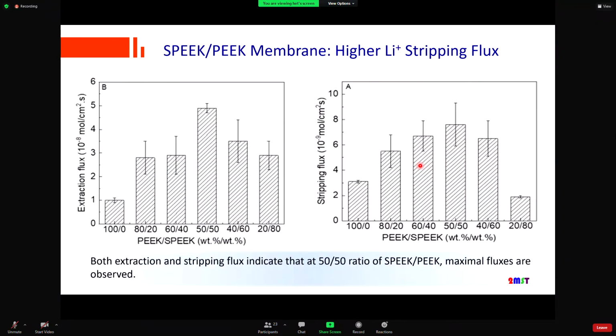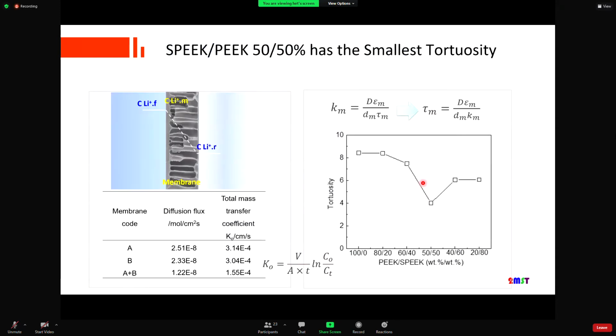For extraction and stripping flux, the two figures show that at a 50-50% ratio, we have the highest extraction flux as well as the highest stripping flux. Why does this membrane show the best performance at 50-50%? It is because at this ratio we have the lowest tortuosity.